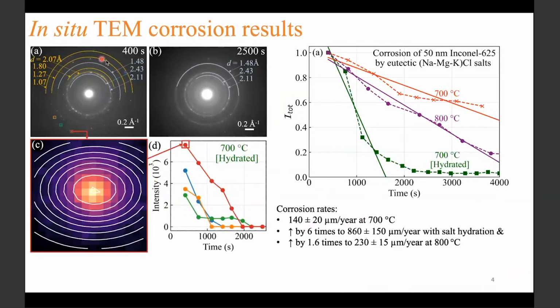The top images that you see here are the electron diffraction patterns that I collected at an earlier time and a later time of corrosion. These diffraction patterns are generated based on Bragg's law of diffraction, which most of us are familiar with in the case of X-ray diffraction, where the periodic structure of a polycrystalline solid produces predictable patterns. In sum, these rings with the spots help us identify the phases or materials present in the system. Each of the spots that we see here corresponds to single grains of the material, or single periodic crystals of the material.